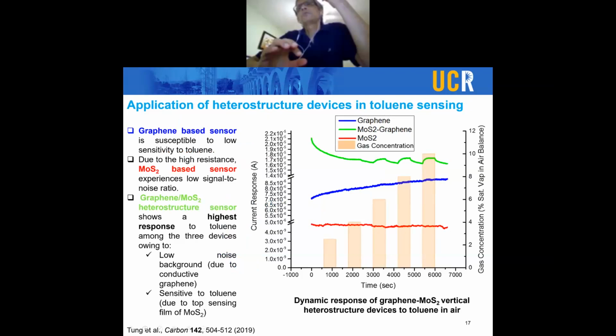And then simply we tested whether our heterostructure was performing better for some sensing application. I stole some of the ideas from Professor Shirsat, who works a lot on VOC. So we decided to test toluene as the VOC. And the results here clearly show that compared to the graphene or compared to MoS2 alone, the heterostructure had a better signal to noise ratio, had a better sensitivity, and it did show that having a heterostructure did provide better sensing characteristic over the native materials. So our first question was answered.